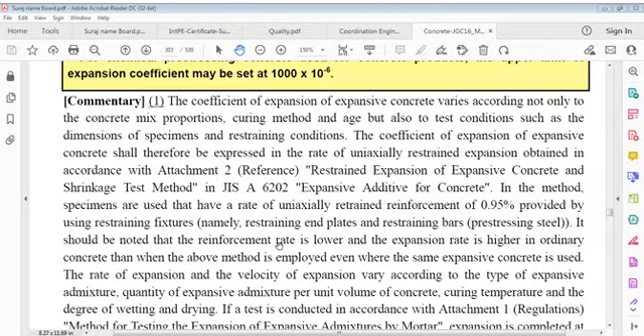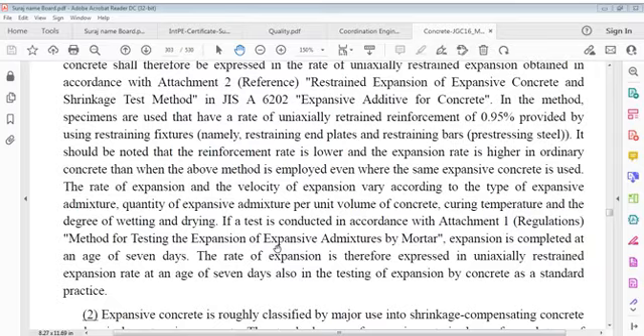The restrained reinforcement is provided uniaxially. In this method, specimens are used that have a rate of uniaxially restrained reinforcement of 0.95%, provided by using restraining end plates and restraining bars, pre-stressing steel. It should be noted that the reinforcement rate is lower and expansion rate is higher in ordinary concrete than when this method is employed, even where the same expansive concrete is used.